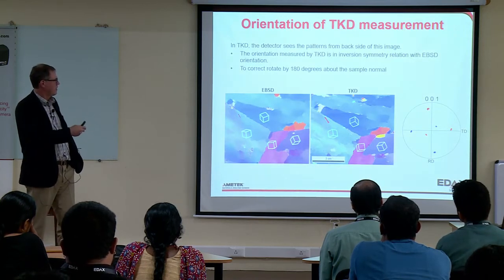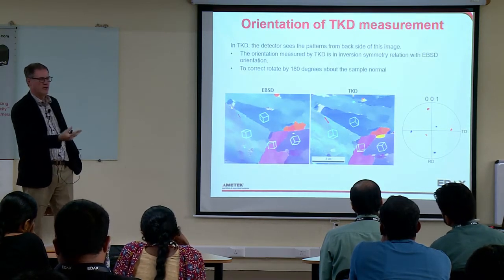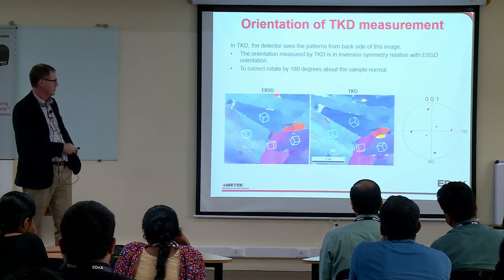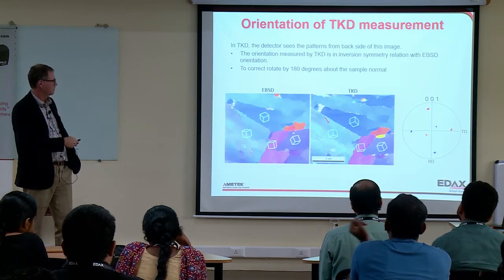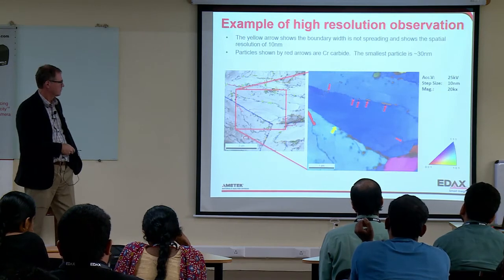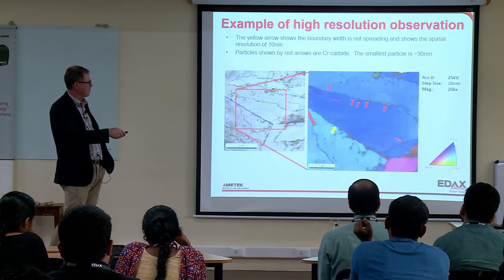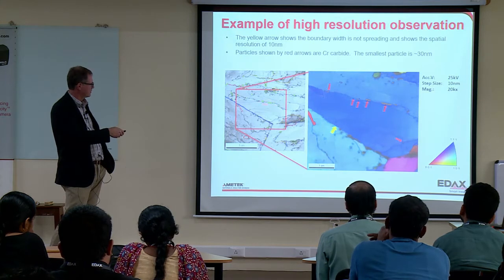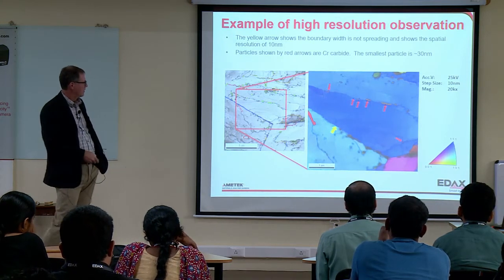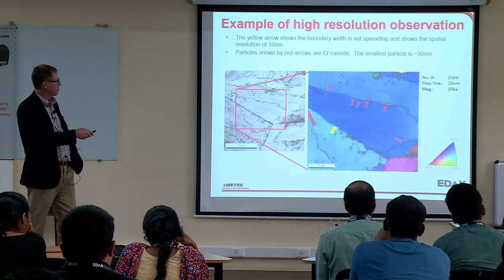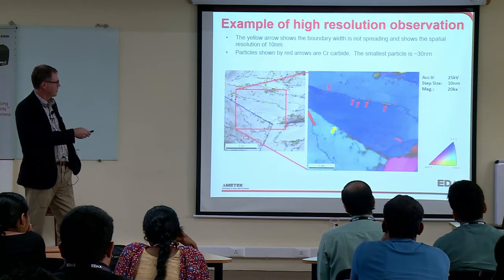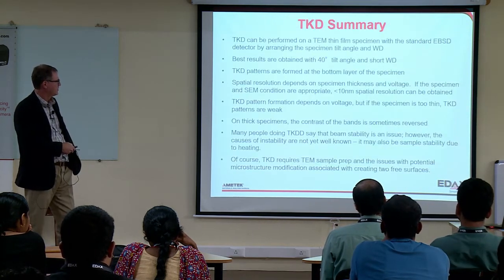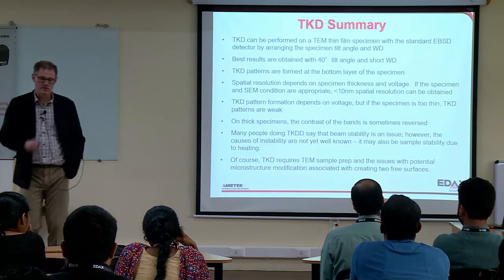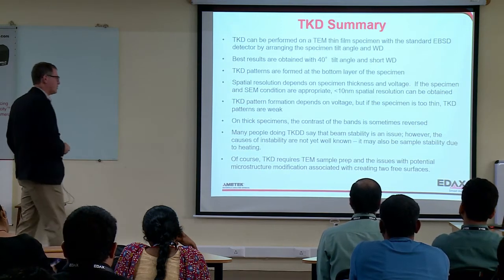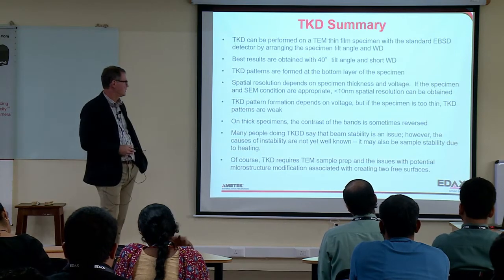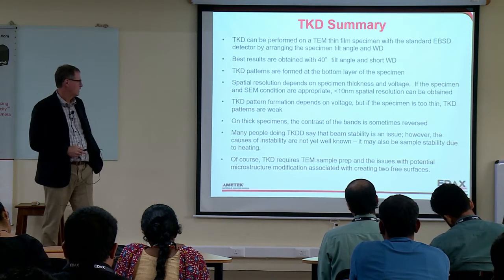So you have to remember we have to do a kind of mirror because now we're looking at back samples, and so you need to be careful with that. But the software will correct for that, so you shouldn't have to worry about it. But the beautiful thing is now we're able to index these carbides right along this grain boundary edge. And so the smallest particle is 30 nanometers, but this is getting pretty old. We can do things down around 10 nanometers or even smaller, maybe even down to 5 nanometers with transmission EBSD or TKD.